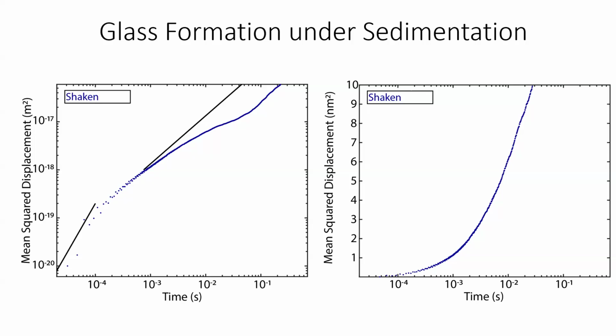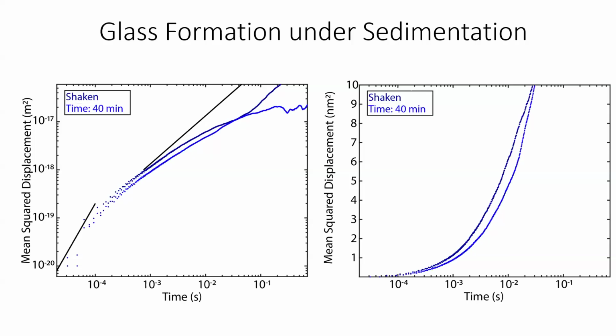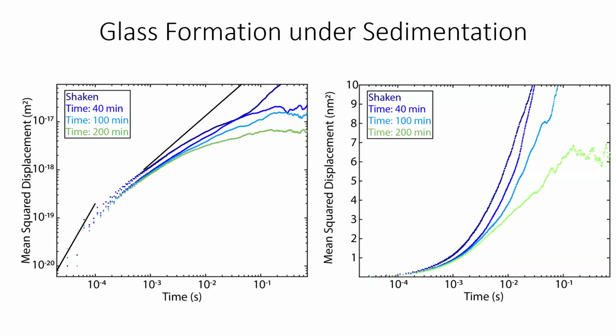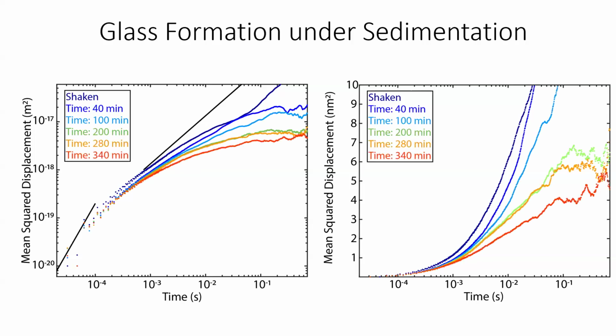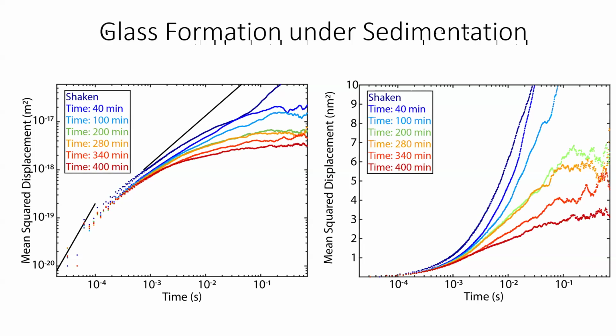And then here, I'm also showing the mean squared displacement versus time on a log linear scale, so that if there is logarithmic behavior, it would show up as a straight line. So as we continue to wait, it in fact does bend over towards something that looks like it's stuck in a plateau. And then this becomes straighter and straighter, looking more and more logarithmic. And so these last two, I've just drawn straight lines. So these would be logarithmic growth lines.